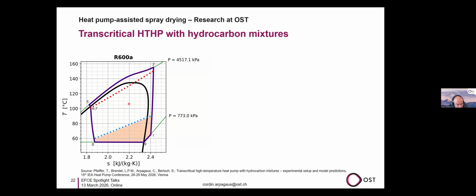Here on the left, you see a TS diagram. So if you are familiar with heat pumps, this is one of our main diagrams to illustrate a heat pump cycle. We have here the evaporation, then the compression, and then the gas cooling with isobutane, another flammable gas, a pure fluid, and then heating up the air or water from 100 degrees to 150 degrees. So the case would be like a coffee spray drying or something like that on the heat sink side. And you see this matches quite well here, the heat transfer. But on the heat source side, the match is not so good. So you see there is quite a difference in the heat transfer temperatures.